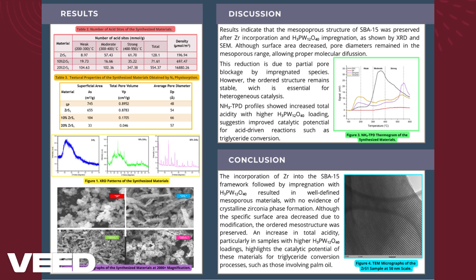The desorption thermograms, Figure 3, reveal that ZR-S1 has a strong peak at 300 to 500 degrees Celsius, moderate sites. 20% ZR-S1 presents peaks at 500 to 600 degrees Celsius and 750 to 850 degrees Celsius, strong sites of different energies, and 10% ZR-S1 shows weaker signals with peaks at 100 to 250 degrees Celsius, weak sites, and around 700 to 800 degrees Celsius. SP exhibits minimal acidity, as indicated by an almost flat profile.